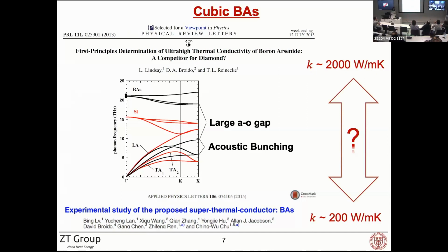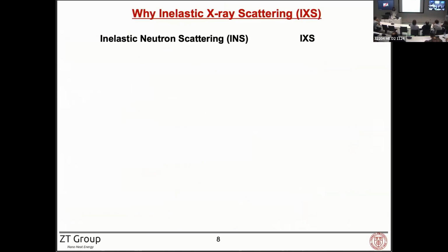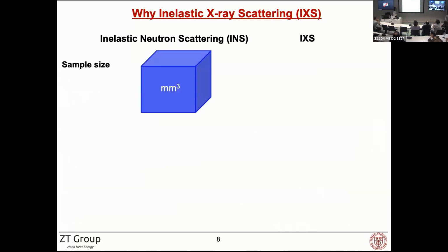Now, to answer this question, we decided to experimentally measure the phonon dispersion to see whether we can see those two key features. To measure the phonon dispersion, there are two popular methods, inelastic neutron scattering and inelastic X-ray scattering. They have their own pros and cons, and I'm going to show you the reason we chose inelastic X-ray for this particular study. Typically, neutron scattering requires much larger sample size, on the order of a cubic millimeter. But with X-ray, you can go with much smaller sample size.